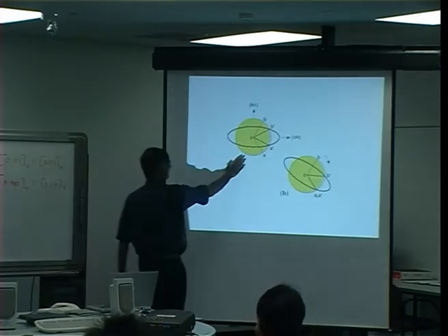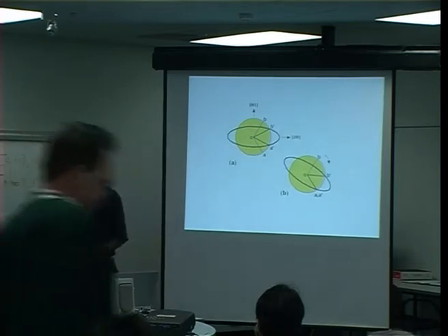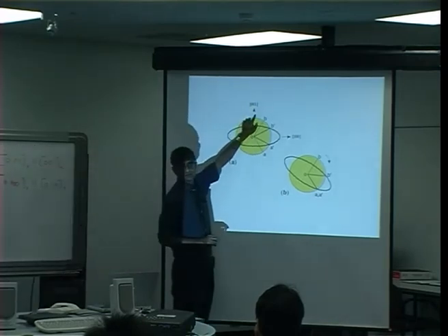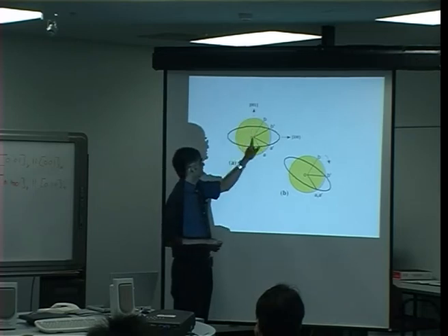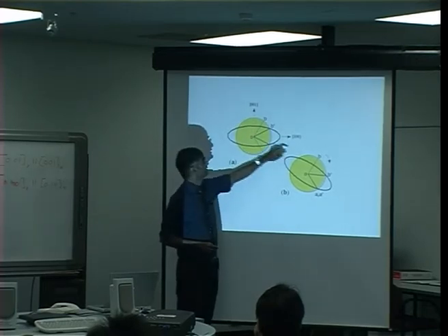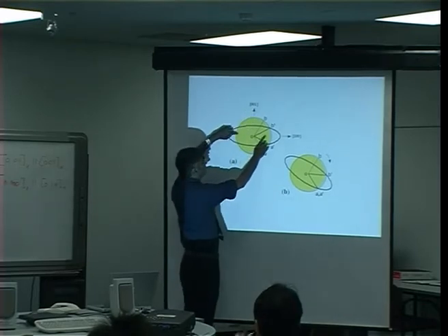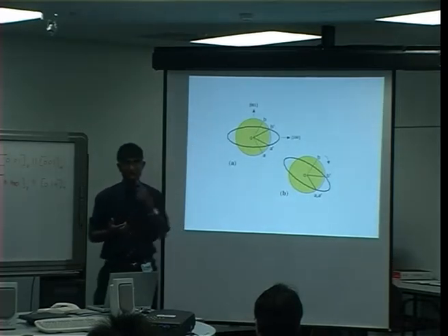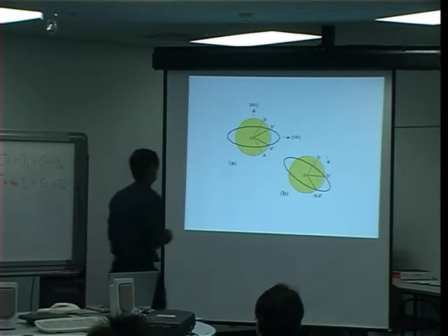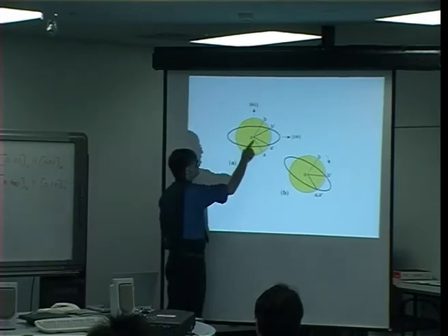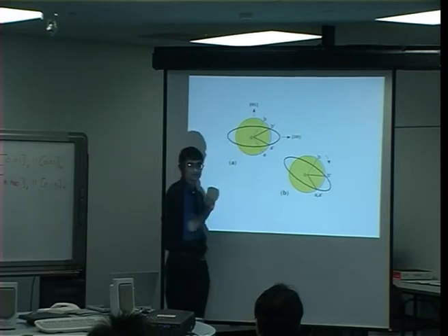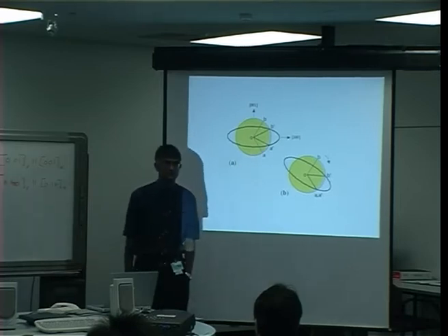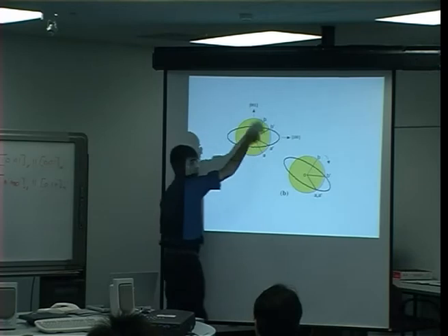So the yellow part here is the sphere of austenite. And I'm plotting here the vertical axis of the unit cell, the 001 direction, and one of the horizontal axes. So obviously, when I compress along here and expand along here and in this direction, I end up with an ellipse of revolution about the vertical axis. Now notice that there are these two vectors here, OA and OB, which as a consequence of the Bain strain don't change in length. You can see that they're still all radii of this circle.